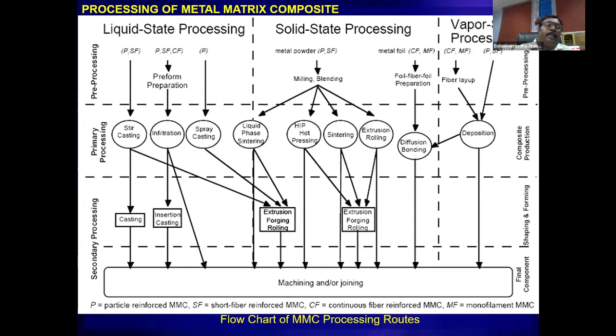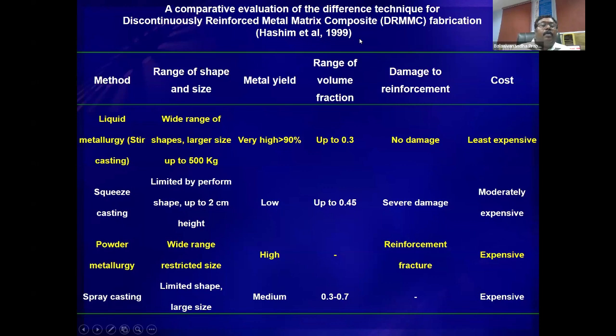Now what I am going to talk about is only the liquid state processing, because that is the technology where, if you overcome the barriers, there is a possibility of mass production. So the industry can think about making good composites in mass production and then use them for different applications. In stir casting, we can have a metal yield of 90%, and the range of volume fraction of reinforcement addition is 0.3. That means 30% of reinforcement in terms of volume can be added. Also no damage would occur to the reinforcement, and it is the least expensive.